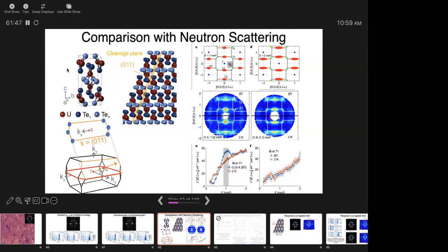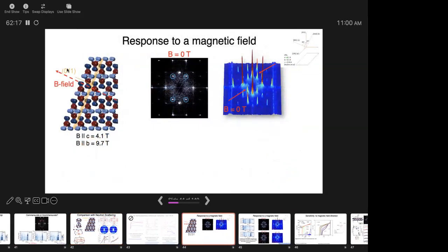We couldn't really find that. We haven't been able to. If you guys have, then you should check. Okay, so quickly, this is neutron scattering data. They see some neutron resonances. I just want to show you where the position of those resonances are. So this is our Brillouin zone. These are our three CDW peaks. And the neutron resonances are here. So our peaks have nothing to do with the neutron resonance. Okay, for whatever that is worth.